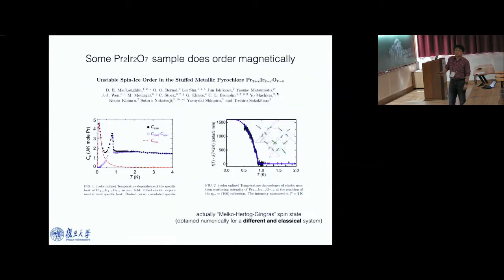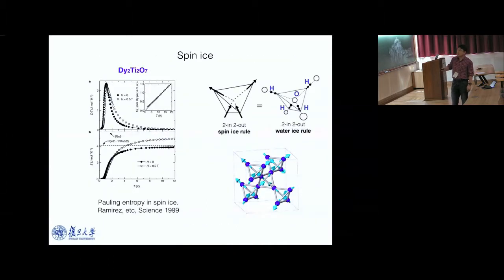So let's focus for the time being on the local moment, and see what the understanding is of the local moment physics. As I said, the local moment comes from the so-called 2-in-2-out spin ice manifold. This is an example of spin ice in dysprosium titanate, where they see the Pauling entropy due to the 2-in-2-out spin ice degeneracy. There is extensive degeneracy for the classical spin ice, because as you cool the system down to very low temperature, the system does not know which 2-in-2-out state to select, and then it just fluctuates within this 2-in-2-out spin ice manifold. There is extensive degeneracy, which was estimated by Pauling and has been measured in this material.